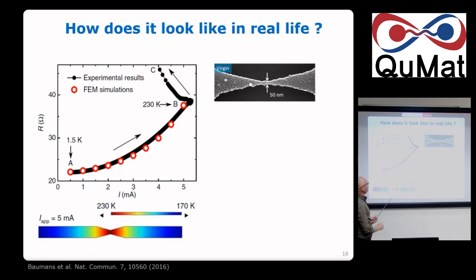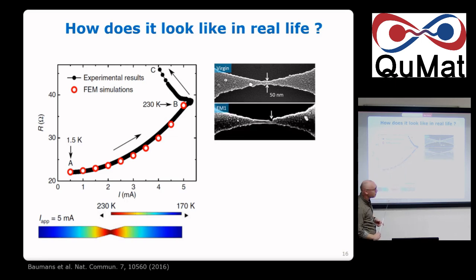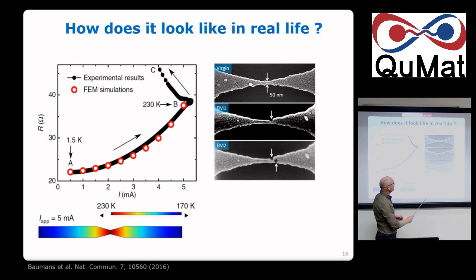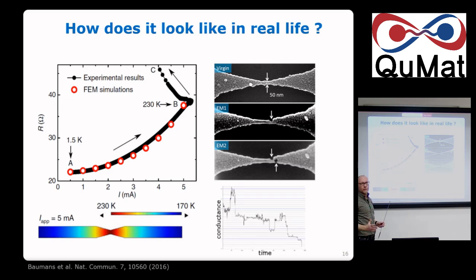So this is the original sample. At that point, it looked like that. We stop, look, and we see where we made a hole in the system. We do it again. We see another hole in the system. But it's getting narrow. So this is by far the limit we can do with electron beam lithography. So we can go down all the way to basically single atoms. We can get quantum of conductance doing this. Okay, so it's a lot of control on the system.